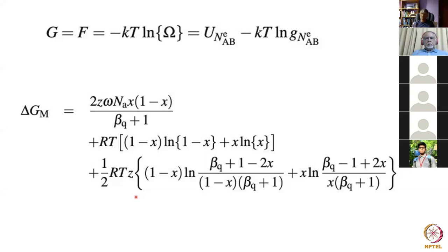When we come to, for example, the diffusion of carbon in austenite, the concentration dependence of the diffusion coefficient is given partly by the fact that the chemical potential is a function of the composition. But in part, it also comes from the fact that the carbon atoms do not ever want to be in adjacent sites within the lattice because they strongly repel each other. That term comes into this kind of factor, beta Q, and provides an additional push to the carbon to diffuse down the gradient simply because the carbon atoms don't want to be next to each other. So you cannot explain the concentration dependence of carbon in austenite simply by saying that there's a thermodynamic factor which comes from the dependence of the chemical potential on concentration.